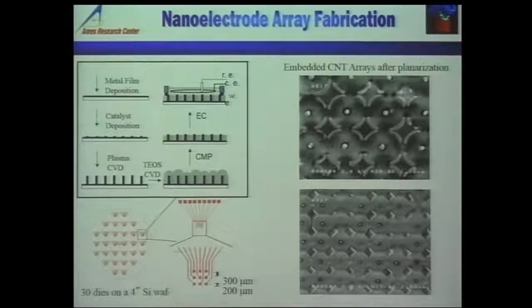We start out with the silicon wafer. We used to do 4-inch wafer, now we do 6-inch wafer, and then we deposit a metal film, titanium, tungsten, tantalum, typically like in microelectronics, and then we put the catalyst deposition for carbon nanotube or nanofiber growth. So here we use nickel, we pattern the catalyst, and then we use plasma CVD, and then we grow vertical carbon nanofibers. Okay? And these carbon nanofibers are about 50 nanometers, and they are about 1.5 micron apart.